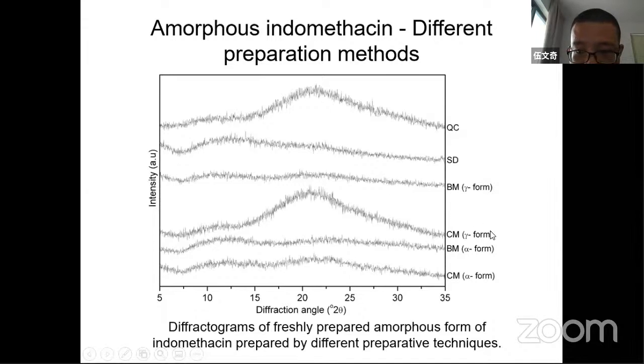If you start from different polymorphs, from alpha or from gamma, or from different starting materials, all of them you can get amorphous indomethacin. This is from XRD results. We can see all of them show no sharp peaks, just a halo, not sharp peaks. So all of them are already amorphous.